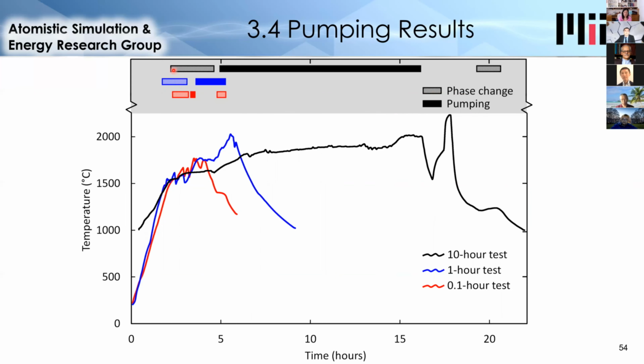So for example, in black, we see a large horizontal region here and another at the end of the test where silicon was melting and freezing. It's horizontal because there's a large amount of silicon and the phase change energy of silicon is large, the latent heat is large. And so regardless of the heat input, the temperature remains relatively constant during this period.